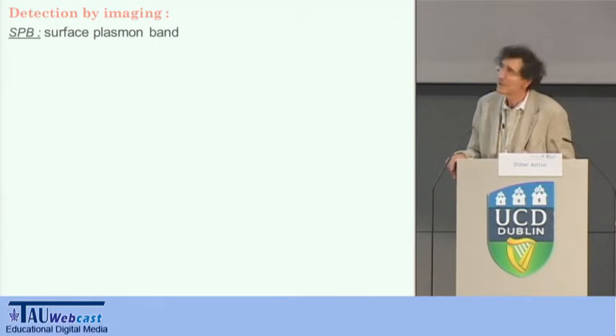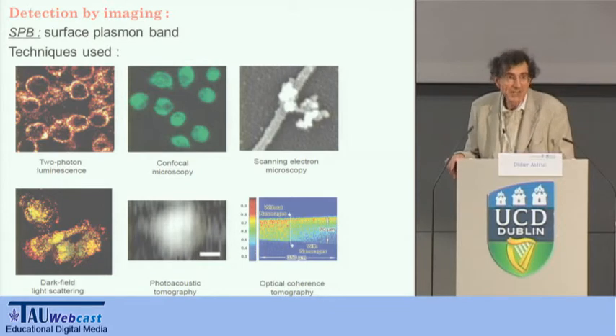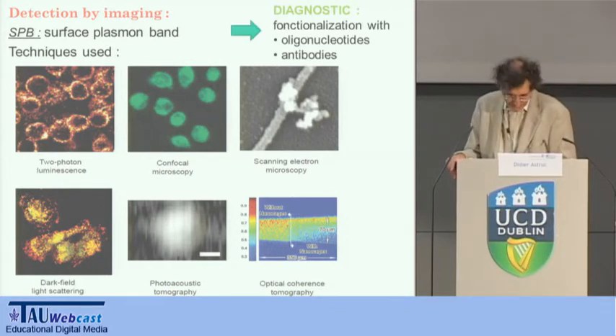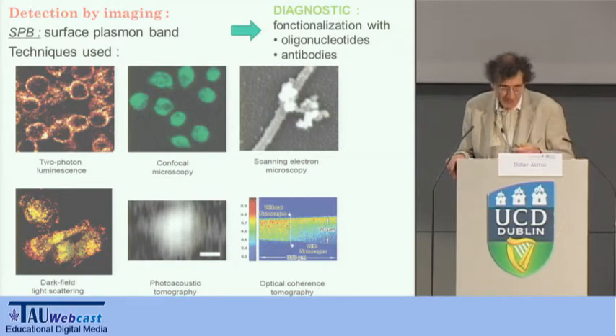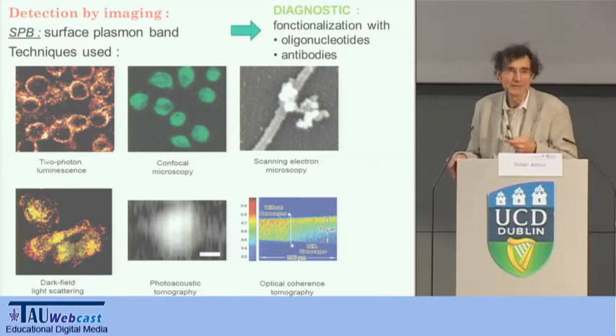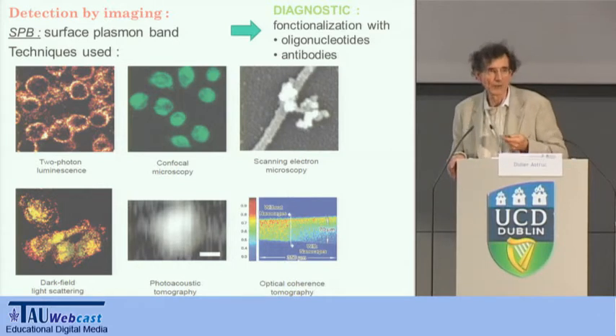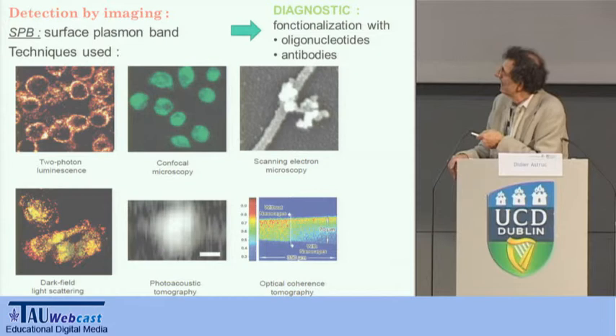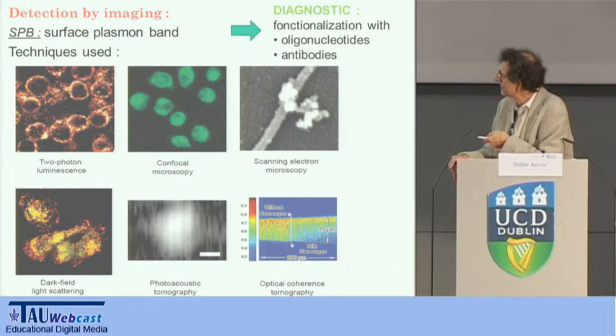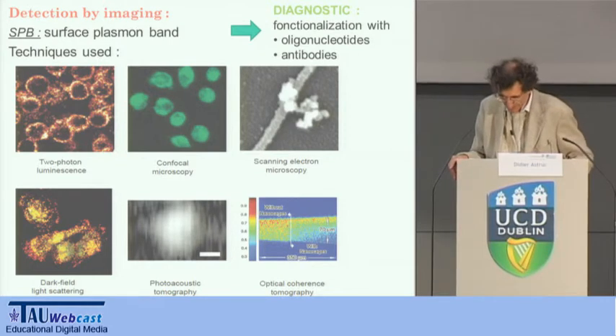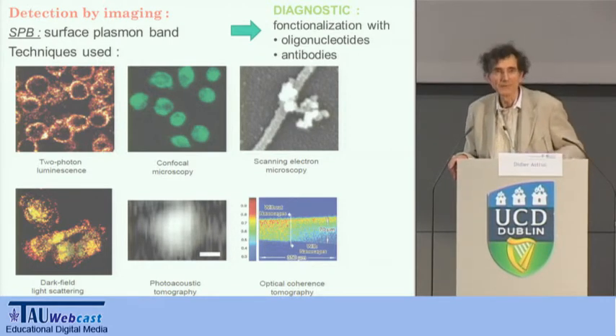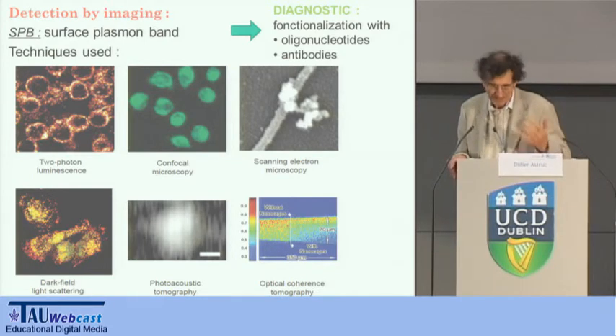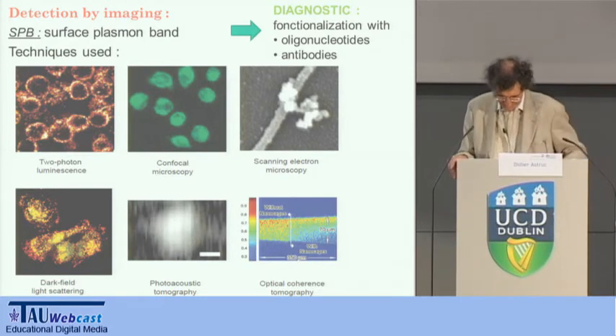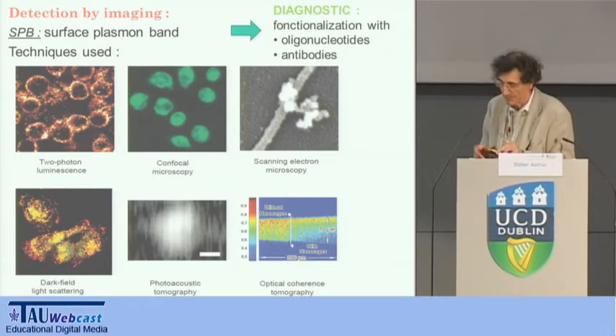So the great advantage of gold nanoparticle is the imaging, and this imaging is important for diagnostics. There are a number of modern imaging techniques in use now for diagnostic using various gold nanoparticles: two-photon luminescence, confocal microscopy, scanning electron microscopy, dark field light scattering, photoacoustic tomography, optical coherence tomography. These are very modern, sophisticated techniques, but all deal with gold nanoparticles. Some of these techniques deal with quantum dots as well. Quantum dots are toxic, gold nanoparticles are non-toxic, so there is an advantage at this point for gold nanoparticle.